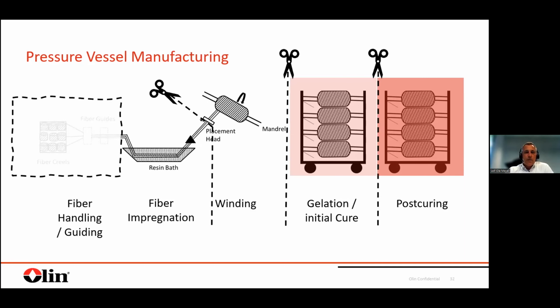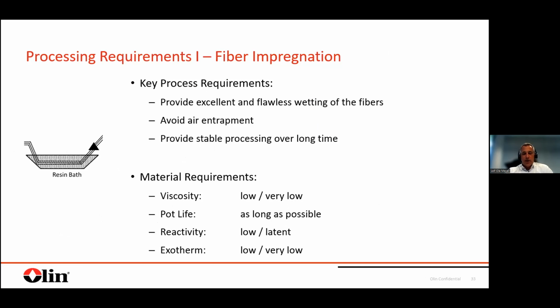So basically, what we decided to do is to use a very, very simple engineering approach. First of all, cutting the process into small pieces. Secondly, eliminate what doesn't have an impact on what we want to talk about. And you can see we are eliminating the fiber handling and guiding. This is where the resin does not yet play an important role. And in the end, we are also simplifying a little bit. So let's start to run through the process, starting with the fiber impregnation. The key process requirement of the fiber impregnation is typically to provide a very good wetting of the fibers, to really cover all the fiber surfaces with epoxy resin, to have no air entrapments or other kinds of bubbles, which would be a deviation from the desired condition.